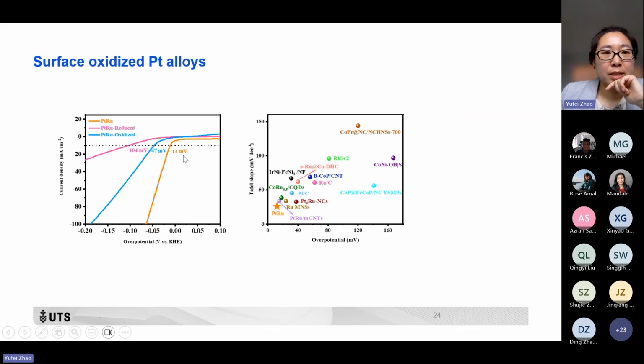When we utilize this material for HER, we found that this platinum ruthenium shows much better performance than the reduced and oxidized platinum ruthenium. So that means the valence state of the platinum ruthenium in the alloys may play quite an important role for HER in alkaline conditions. And currently, we are utilizing in situ characterizations to further investigate why this change of the valence state can highly affect the HER performance.